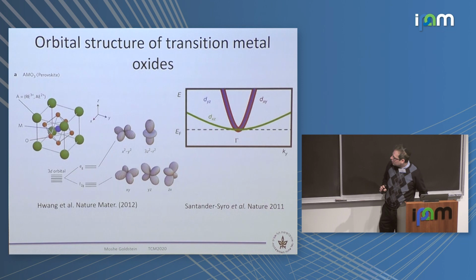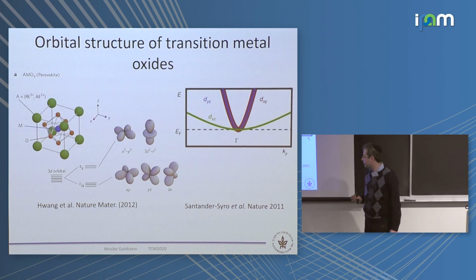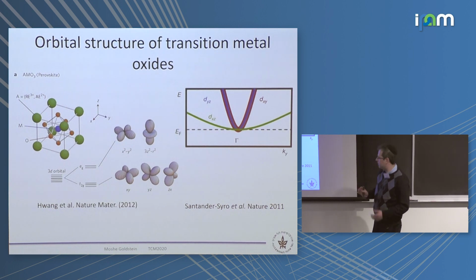Now, in terms of electronic properties, undoped strontium titanate is an insulator, but when you dope it, things start happening, and the orbitals in which things start happening are the titanium 3d orbitals, which in the crystal field split into t2g and eg. The eg go upper in energy, so they are not important, but the t2g basically form the conduction band, and when you dope, those are going to play the important role. And because of their structure, just because of considerations of the overlaps of nearest neighbors, let's say the xy would give rise to a band which has a low mass, high mobility in the x and y plane, and high mass in the z direction, and similar things for the other orbitals. Again, this is going to be important soon.